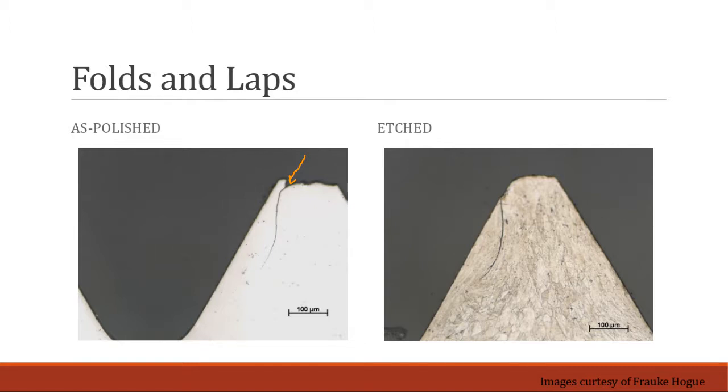If you're rolling threads during the forming process, there's a chance, if you have a burr in the material, or just material that wasn't fully cut, or a misalignment even with the machine, the material will fold over upon itself, and in doing so, the material, after you etch it, will show deformation.